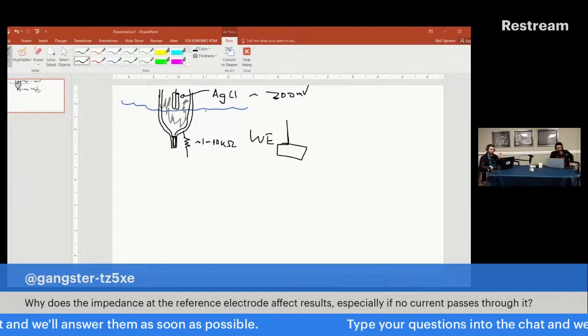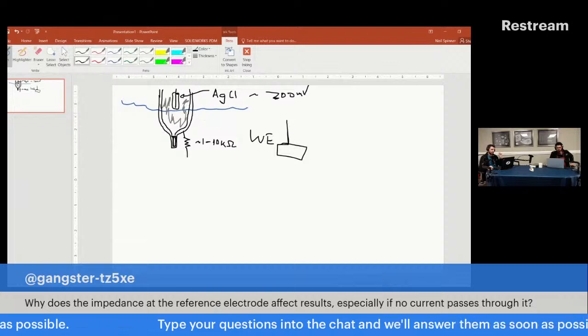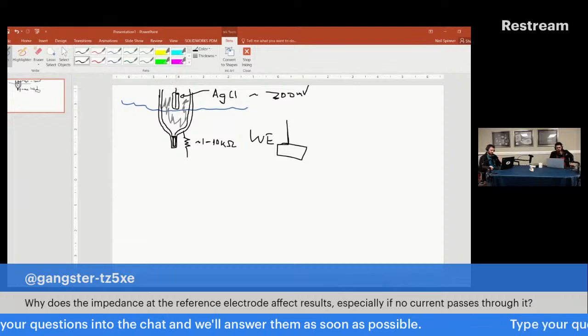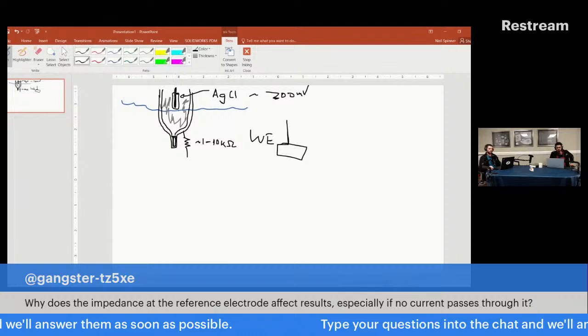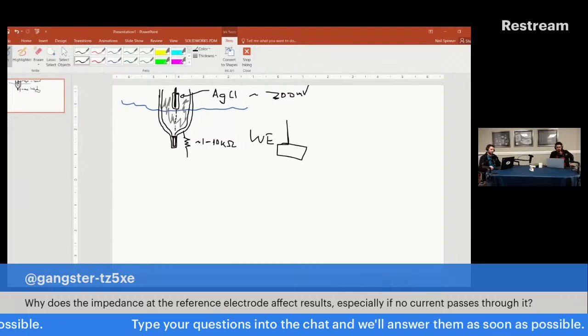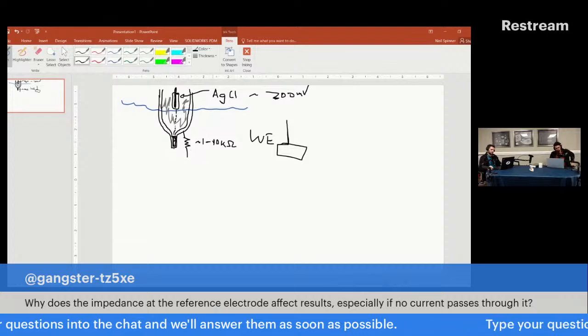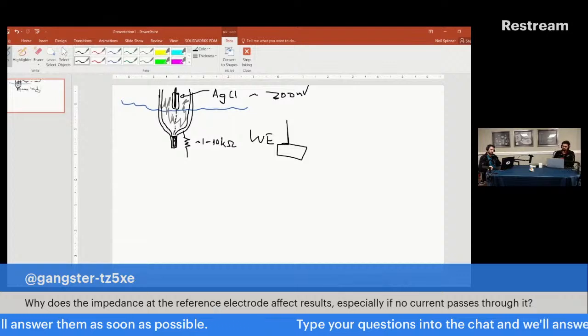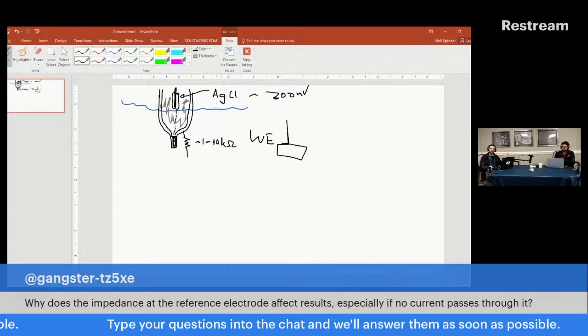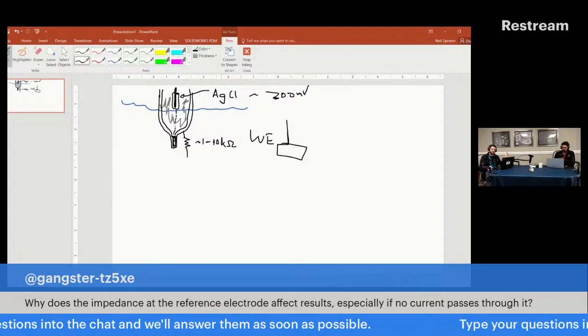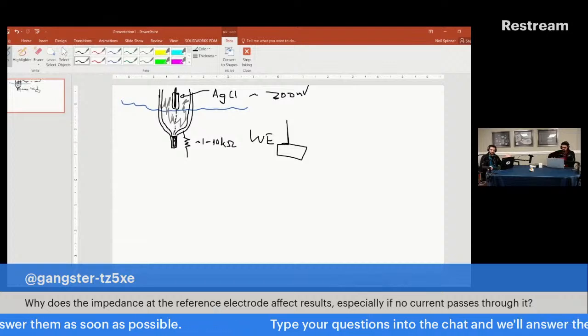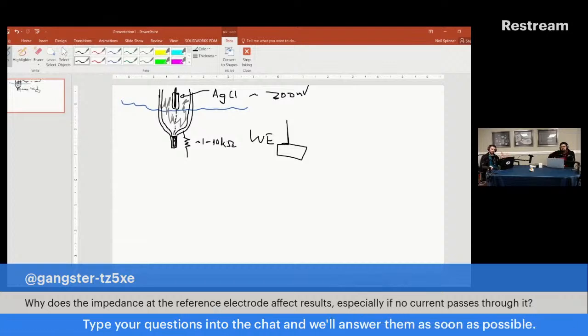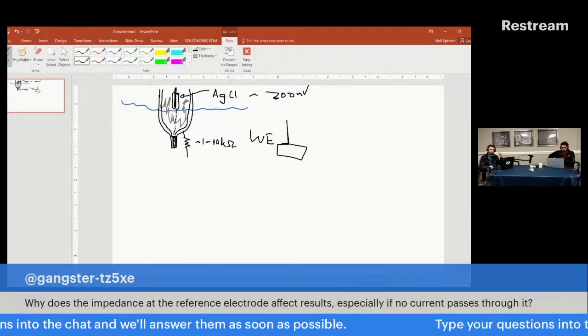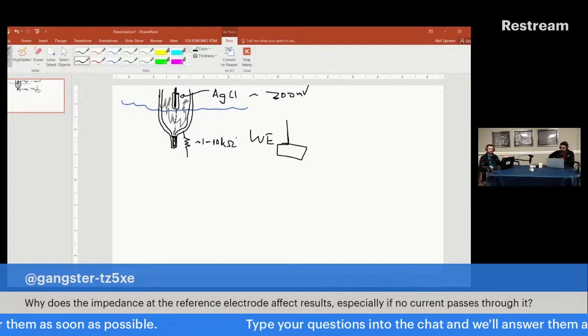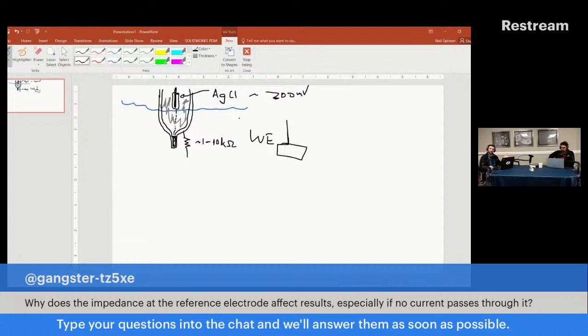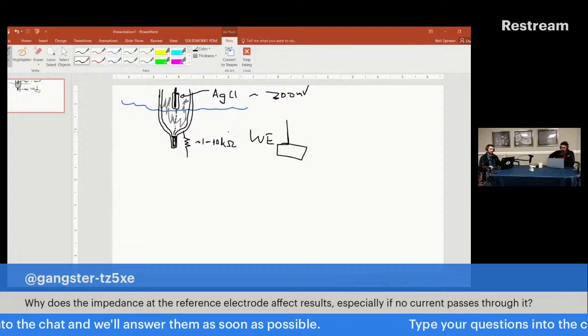The connection that we have in solution here is such that it goes through this Ag wire, which is perfectly conductive. There's no resistance, basically, right? Through high concentration electrolyte, and then through this frit, this resistance, which has this much impedance. Okay. If there is any other pathway electrically of communication that has lower than 10 kilo ohms or 1 kilo ohm of impedance, the potentiostat will select that pathway, right? Current, electrical communications in general is like water. It will follow the path of least resistance or least impedance, right?